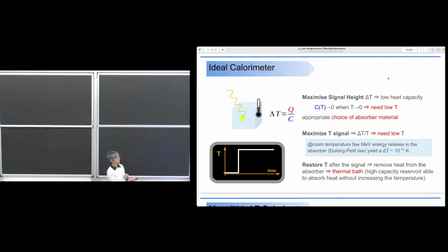This is an example. If you assume to have a MeV energy release in a solid at room temperature, and you use the Dulong and Petit law for the heat capacities, you will see that you have a temperature increase of the order of 10 to the minus 12 Kelvin. That is extremely small, and you understand that there is no way of measuring this kind of increase in temperature, because it is more than 12 orders of magnitude lower than the room temperature.